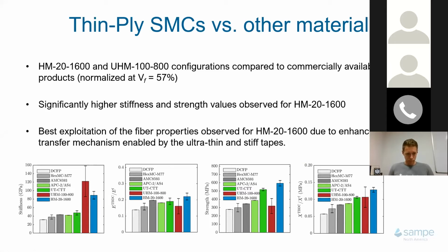Okay, exactly. So in that slide, we were comparing the thin ply SMCs, manufactured with the Textreme spread tapes, and some other SMC products that are either available in the literature or already commercially available. The purpose of this comparison was also to compare the different material systems. The specimens didn't have the same thickness, because for some SMC products manufactured with standard materials, a very thin sheet thickness is not achievable. So those specimens had a higher thickness. And then, of course, the thin ply SMC, as we discussed, has a lower sheet thickness, even lower than 0.5 millimeter.